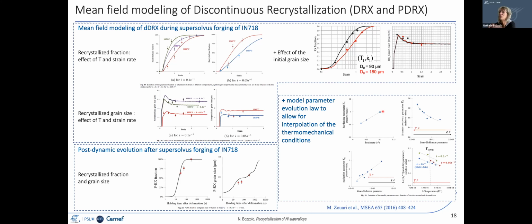the microstructure evolution, not only for one nominal set of thermomechanical conditions, but for varied conditions, and notably at the scale of an industrial piece, you never have a homogeneous temperature and strain rate throughout the piece. So you need to have these parameters calibrated as a function of local thermomechanical conditions, so that you can calculate the microstructure evolution at any location in the big piece. All right.